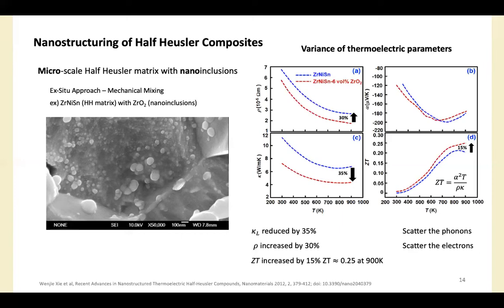The purpose of sintering nano inclusions is to scatter heat-carrying phonons and subsequently reduce the resulting lattice thermal conductivity. As observed in the graph, the lattice thermal conductivity was reduced by 35 percent as compared with the original half-Heusler compound. Because particles are distributed at the grain boundary, they behave as phonon scattering centers in order to scatter the heat-carrying phonons. Therefore, the phonon mean free path is reduced. Accordingly, the lattice thermal conductivity reduced. However, due to scattering of electrons, electrical resistivity has increased. Even though there is a decrease of electrical conductivity, the value of ZT increased by 15 percent at 900 Kelvin.